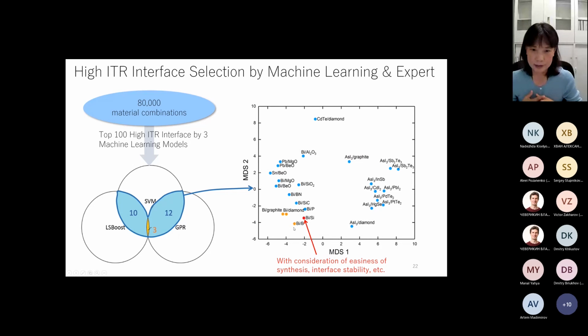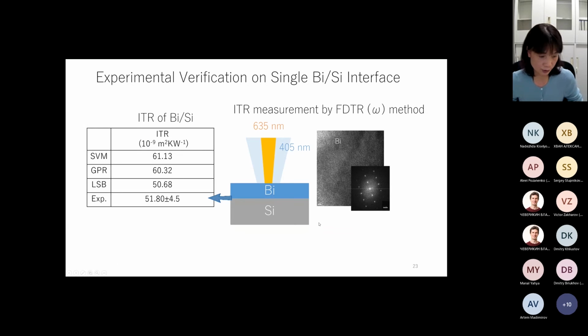But when we consider material development, we have to think about the ease of synthesis, stability of the interface, environmental hazard, cost, and others. And finally, we select the bismuth-silicon interface for experimental verification. The first thing we do is build a single bismuth-silicon interface by depositing a bismuth film on a silicon wafer, and measure the interfacial thermal resistance of this single interface.